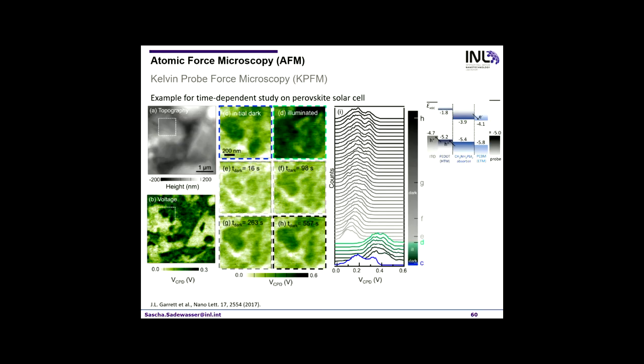So they analyze this by histograms. So we start here in the bottom. This is the dark image. Then under illumination, that's during this time here, they have light on, so we get quite a significant change in the CPD. And then when you switch off the light, you don't come back to this one, you get this shape. And then with time, and this is the final image here, they go back to this.